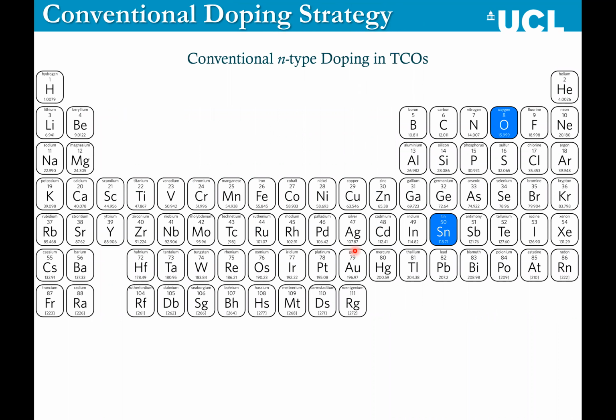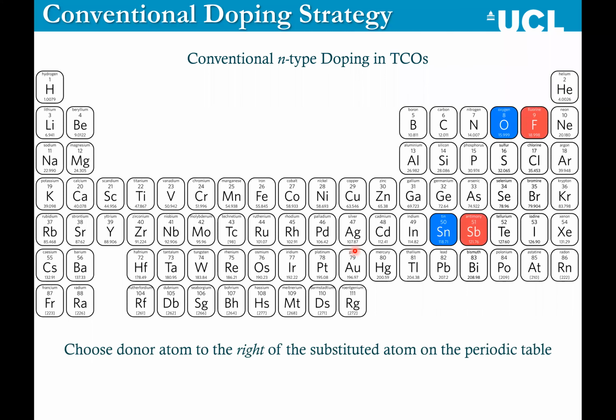So conventional doping strategies are the same as you would use for doping semiconductors like silicon. Typically, if you have a material like tin dioxide, where you have 4 plus tin, and obviously oxygen is 2 minus, you would go 1 to the right in the periodic table, replace tin with antimony 5 plus, and you would replace oxygen with fluorine 1 minus. These atoms have 1 extra electron, so you're n-type doping your system. But because they're side by side in the periodic table, they're about the same size, so you don't have too much of a strain problem. They should fit in the site that they're replacing.